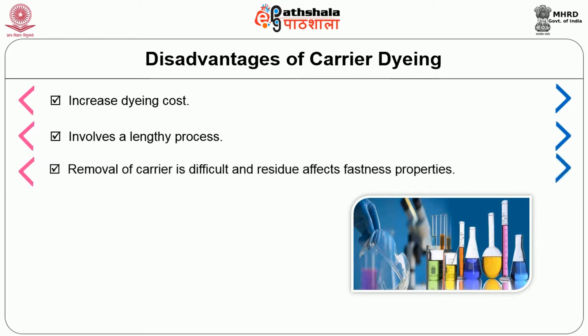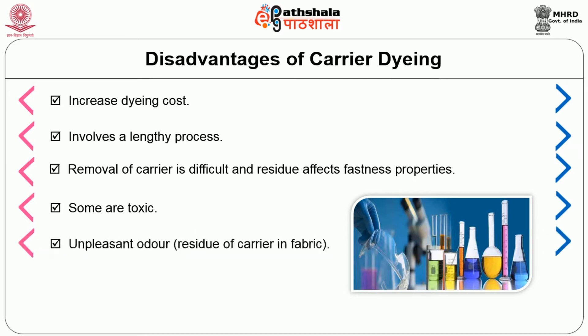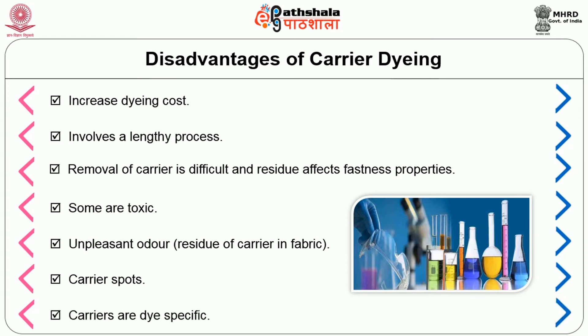Disadvantages of carrier dyeing: carrier dyeing increases the dyeing cost, involves a lengthy process, and removal of carrier after dyeing is very difficult. The residue of carrier on the fabric affects fastness properties. Some carriers are toxic and are banned, and this process is almost obsolete. The residual carrier in the fabric gives an unpleasant odour. Carrier spots form if the carrier is not removed properly. Carriers are dye-specific — specific carriers are used for specific dyes — and not all carriers are suitable for all dyestuffs.